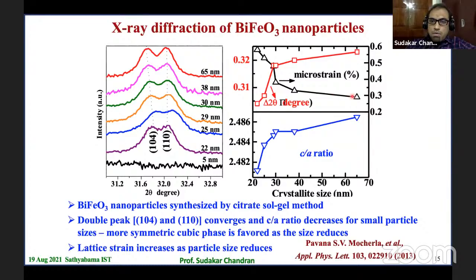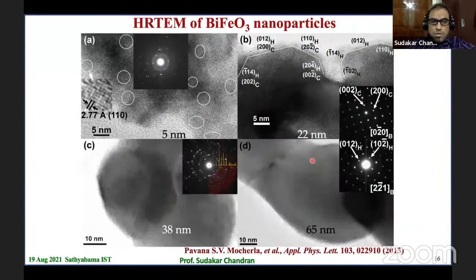The microstrain, as you decrease the size, increases a lot, especially around 30 nanometer. And at the same time, you see the lattice parameters also change a lot, specifically the C by A ratio. So the microstrain that comes because of the size effect has an influence on the structure. Here is the example of the 5 nanometer crystals we had. Of course, there's a large component which is amorphous. But as you increase the size from 5 nanometer to 22, these are all average sizes that I have pointed out, and 38 and 65 nanometer, more and more larger, well-ordered crystallites are obtained.